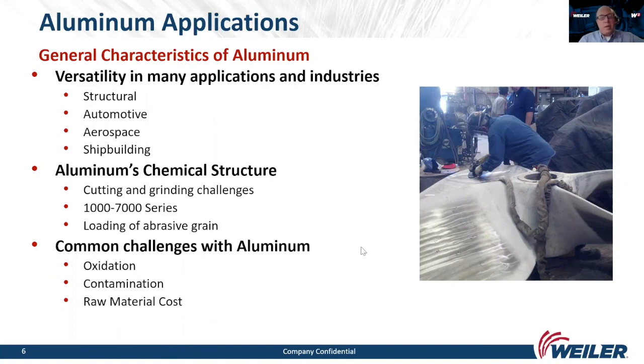Also, the possibility of contamination is more prevalent with aluminum than it is with common metals like steel. Just like with working stainless steel, with aluminum you have to be careful. When you've got a dedicated wire brush or abrasive, make sure it stays dedicated to the aluminum and you don't switch to another kind of product that you're going to be grinding on. Don't switch to steel and come back to it. You'll produce cross-contamination. Make sure that the wire, again, is stainless steel, not carbon steel. And make sure that the abrasive you're using is specifically designed for aluminum and also does not contain iron.